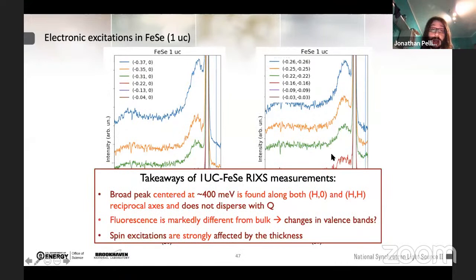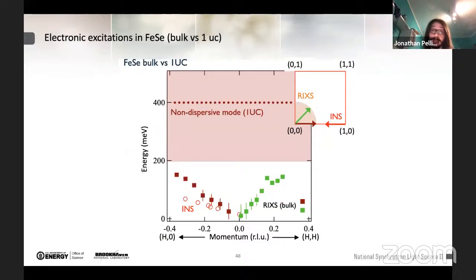Now here, I want to give a few takeaway messages. In the one unit cell material, we have this 400 meV excitation that does not disperse as a function of Q. Additionally, we have a fluorescence that is pretty different from the bulk, and it implies a pretty strong change in the valence band. And finally, if we consider the spin excitation, this implies that the low energy spectrum is pretty different and affected by the thickness.